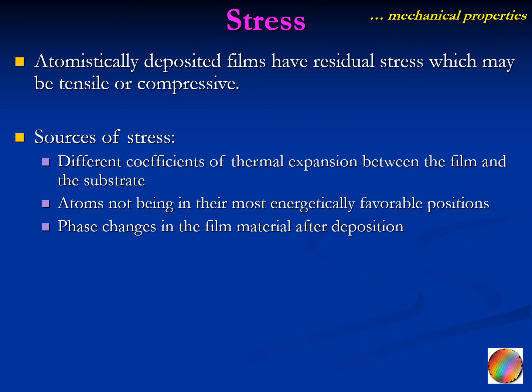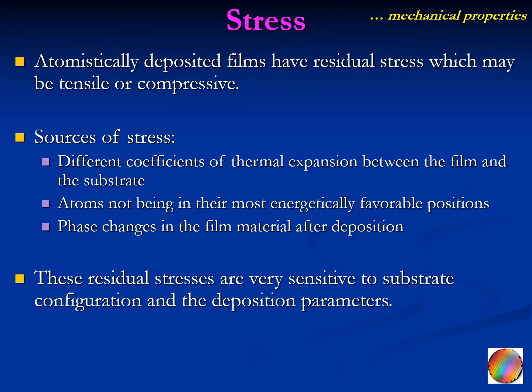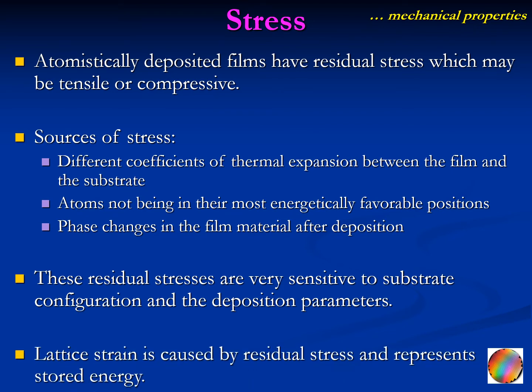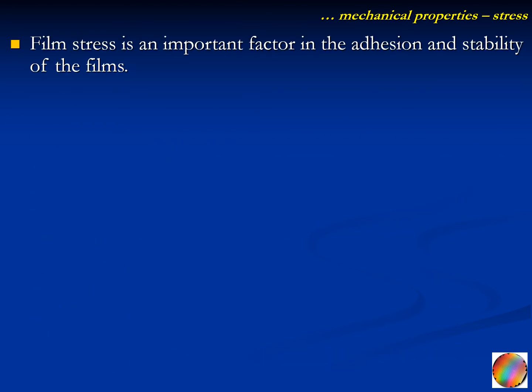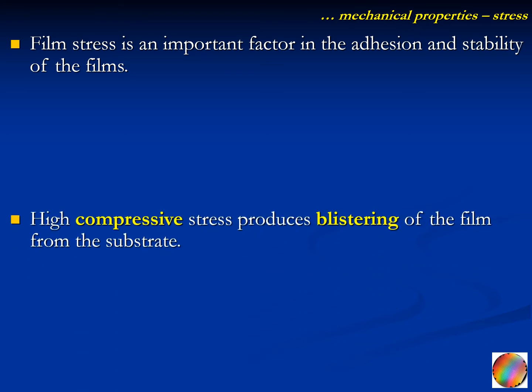The sources of stress include different coefficients of thermal expansion between the film and the substrate, atoms not being in their most energetically favorable positions, and phase changes in the film material after deposition. These residual stresses are very sensitive to substrate configuration and the deposition parameters. Lattice strain is caused by residual stress and represents stored energy. Film stress is an important factor in the adhesion and stability of the films.